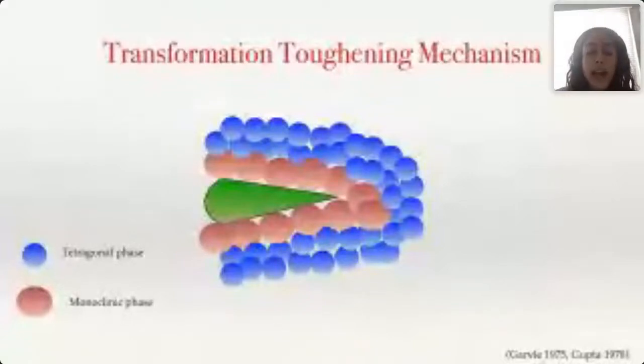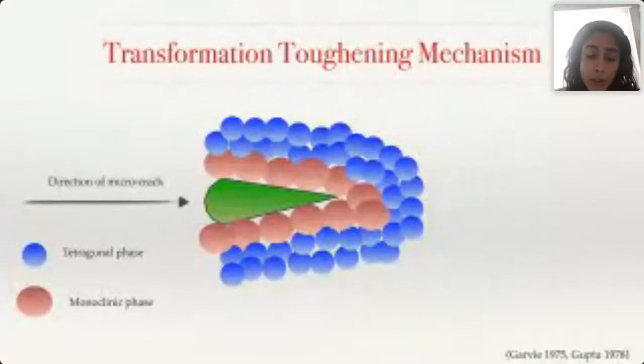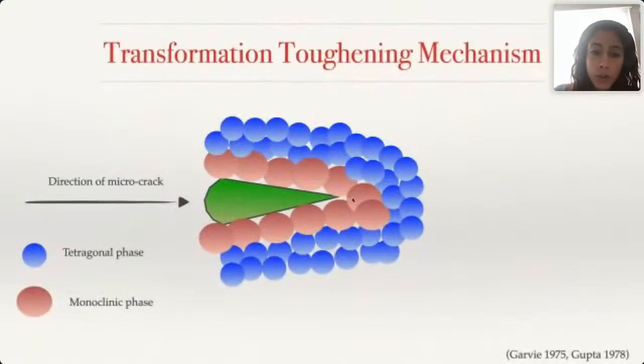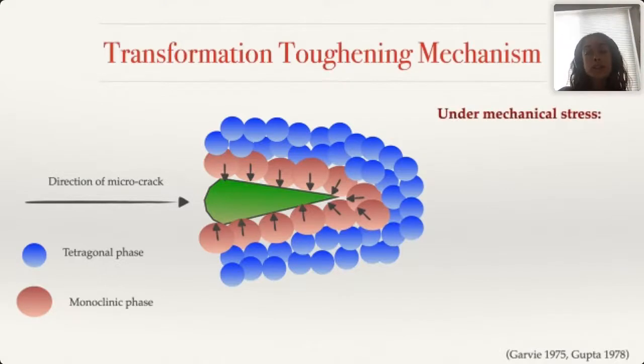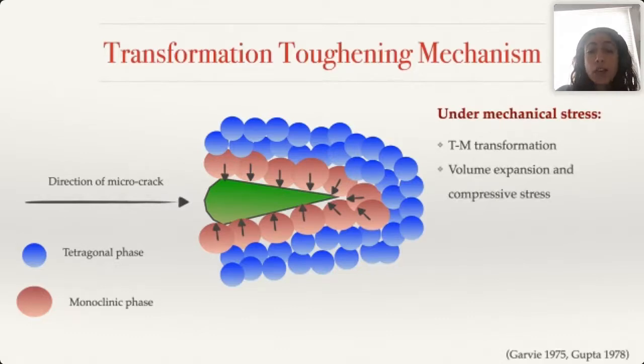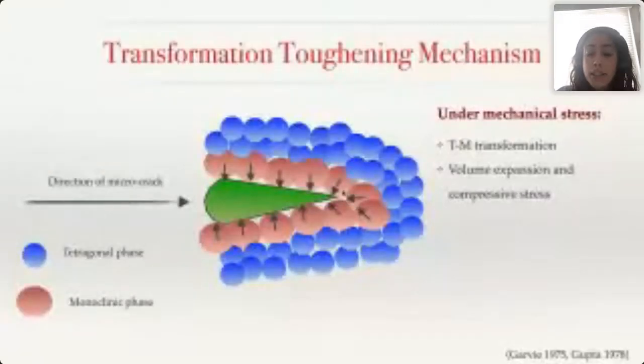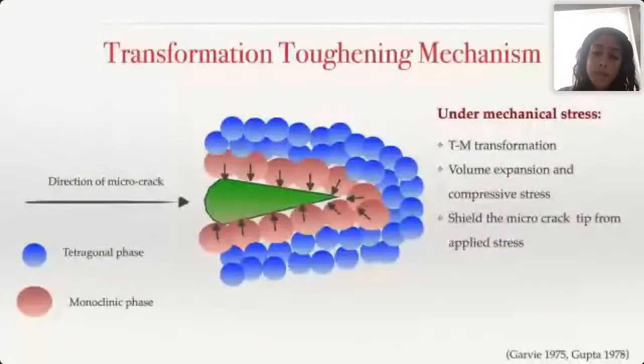Stabilizing the grains at the tetragonal phase has another advantage. If you think of a cross-sectional cut of the material with all the zirconia grains, and there's mechanical stress causing micro crack formation, the grains on the surface actually close the crack. This is interesting because the grains change in response to the micro crack — from tetragonal to monoclinic — creating an increase in size and volume, increased compressive stress, which shields and closes the microcrack. That's why these materials are tough and don't fracture easily, due to this transformation toughening mechanism that prevents the Y-TZP material from fracturing.